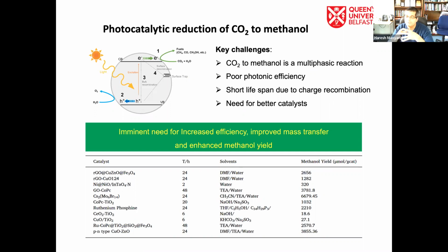And in the current methods, the photonic efficiencies are low and the lifespan of the charge carriers is very low because of the charge recombination. So what happens is on the surface of the metal oxide, when you shine light onto it, it generates the pair of holes and electrons, which then recombine because of the surface recombination, then the efficiency is poor.